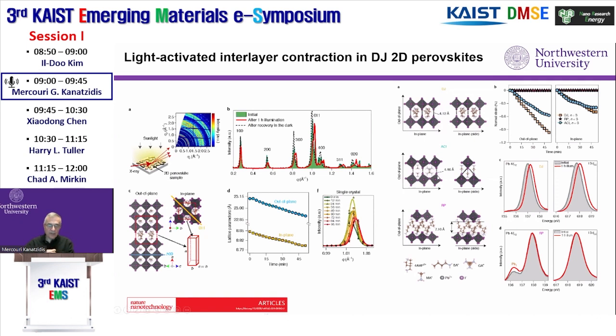Upon illumination, you see a remarkable result where there's a contraction, indicated by the diffraction pattern. In fact, the lattice gets contracted, and the most contraction in the lattice parameter, especially in the stacking direction, happens in the Dion-Jacobson, which is shown here, out-of-plane contraction. However, in the Ruddlesden-Popper, which has very long distances and the layers really don't communicate, nothing happens. No contraction, no expansion, or anything else. And there's some contraction in this one here. So that was surprising. Why was that happening?